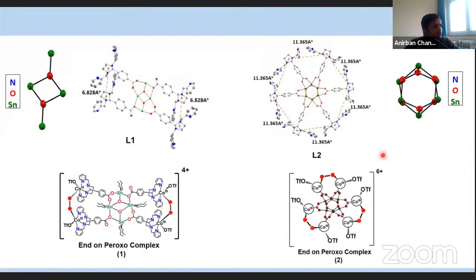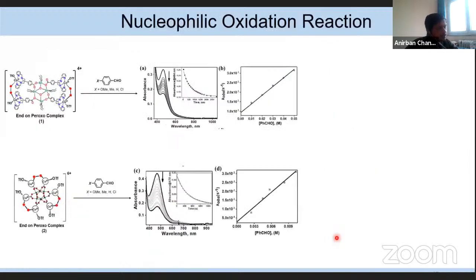So far I showed you the tetranuclear ligand, which is containing the Sn4O2 backbone, and hexanuclear ligand, which is containing Sn6O6 backbone. And from these two ligands, I synthesized two cobalt complexes, and after oxygenation, I get one endon peroxo complex, and here the endon peroxo complex for the hexanuclear complex is 2. So we are also interested to see how it's reactive towards the external substrate.